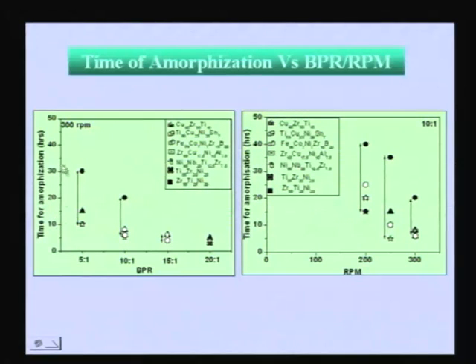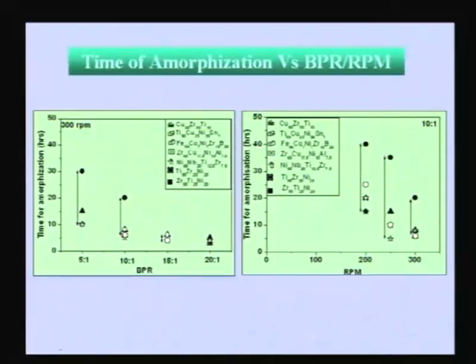And again, the time required for amorphization, if you look at various systems, one can see that at very high milling energies, that means high ratios and high RPM, the overall time required for amorphization is the same irrespective of the system that you choose. When you are putting in so much energy, every system becomes amorphous very easily. As I told you, if you use a laser for rapid solidification, even a pure metal can become amorphous.